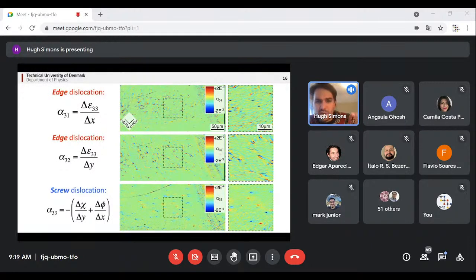So in this system, which is bismuth ferrite grown on dysprosium scandate, you should in principle have misfit dislocations, and these should move along particular lattice directions. And in this case, these two panels corresponded to the density of edge dislocations, and the lower panel corresponds to the density of screw dislocations. In particular, if you look at the lower panels, you'll see you have blue dots and red dots. And if you integrate the density around one of these blue dots, you get a density of negative 1. And if you integrate around one of these red dots, you get a density of positive 1. That's because each red dot is an individual dislocation and each blue dot is an individual dislocation, and the sign corresponds to their chirality.